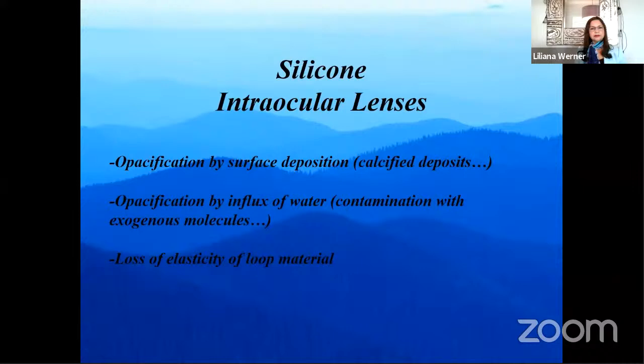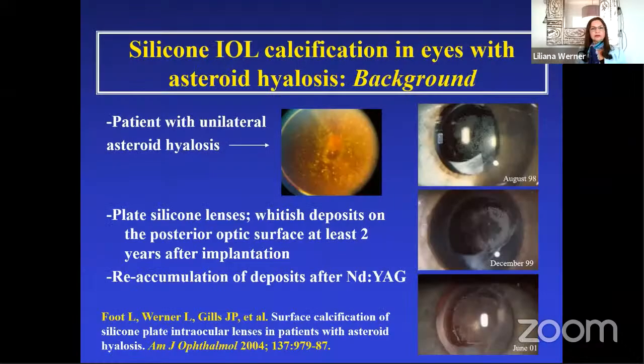Different issues may lead to opacification of silicone lenses in the postoperative period, such as surface deposition and opacification due to influx of water in these lenses that are normally highly hydrophobic. Here, we will also discuss an interesting problem of loss of elasticity of the loop material leading to dislocation. Silicone IOLs may also calcify, but this has been only observed in eyes with asteroid hyalosis.